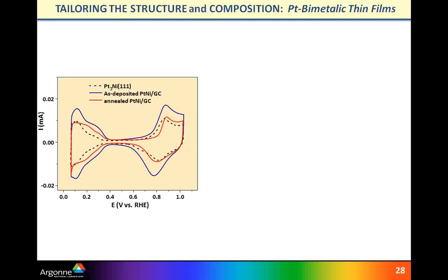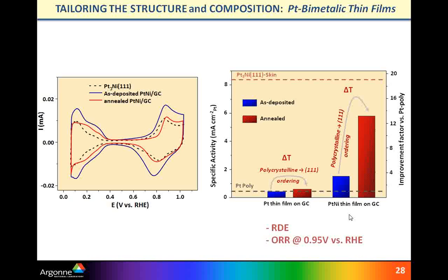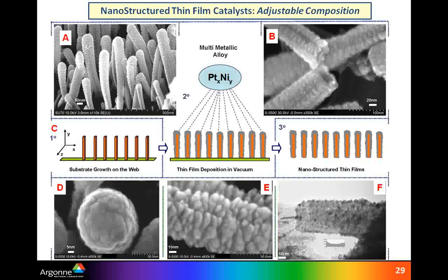as well. And our next step was to explore how all of that would work on corresponding platinum-nickel bimetallic systems. And here one can see voltammetry of as-deposited versus annealed. But what is more important was to check catalytic properties. Initially, the polycrystalline film after annealing became indeed 111-like, which is confirmed by extremely high catalytic activity, which was as high as 75% of the most active platinum-3 nickel 111 skin surface. And that inspired us to go back and see how all of that can be applied to practical catalysts.